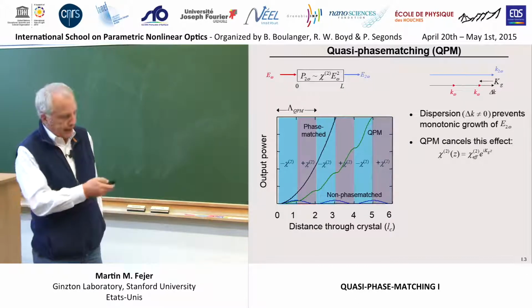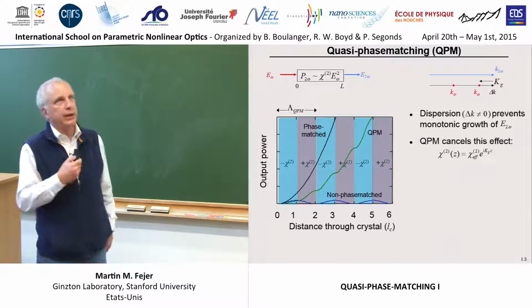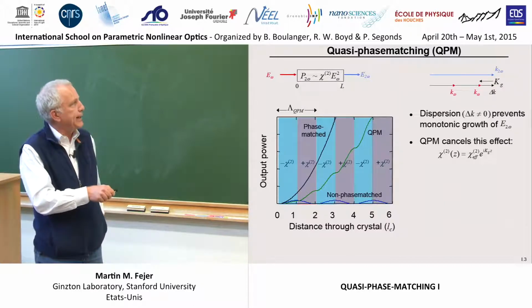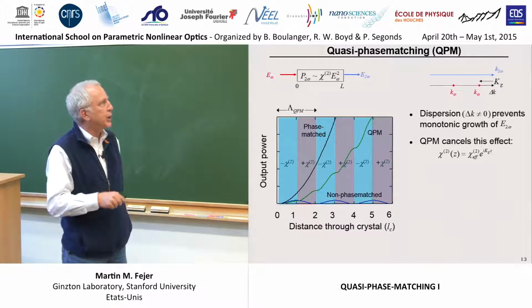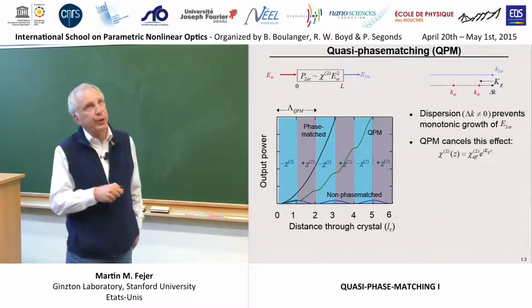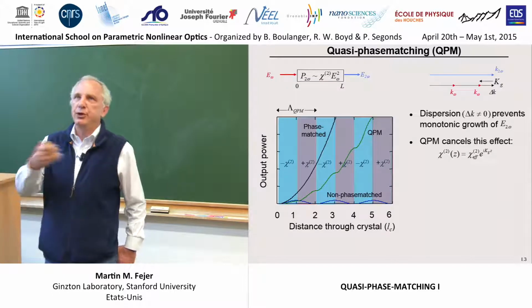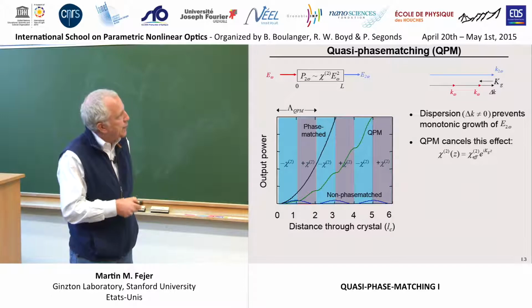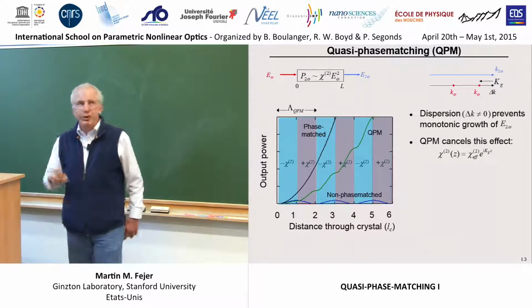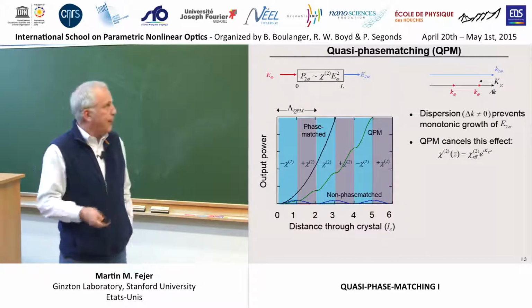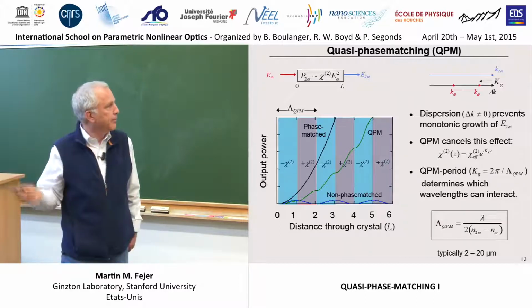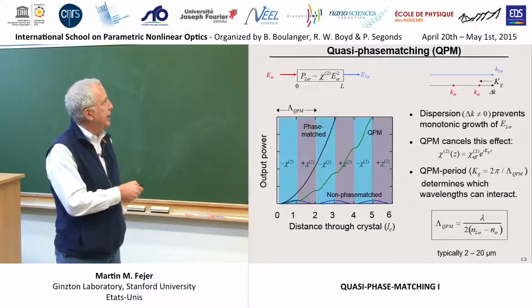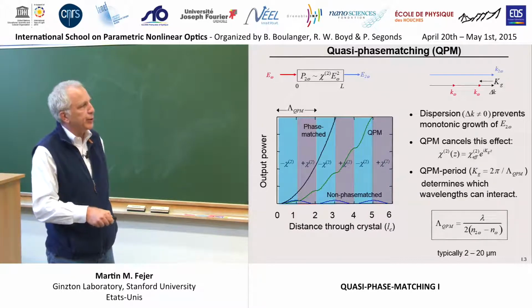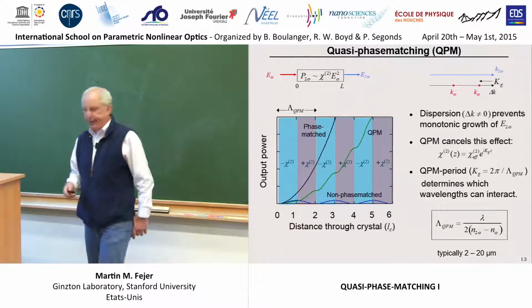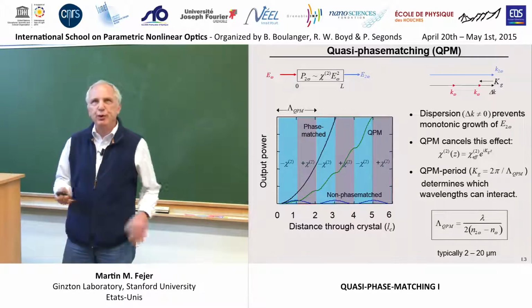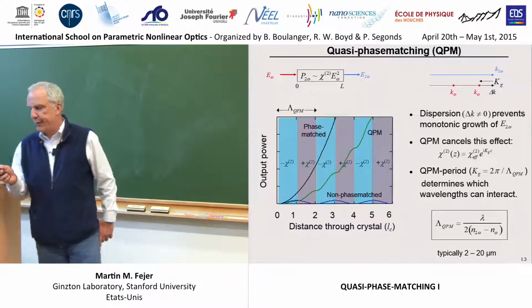An alternative, as we've also heard several times in the recent lectures, is quasi-phase matching. If one imposes a periodic sign change on the nonlinear susceptibility, adding an additional periodic structure and thus an additional k vector in the problem, one, instead of conserving momentum, can conserve something like a quasi-momentum to the extent that this periodic structure is just the right k vector to compensate for the phase velocity mismatch delta k. In such a situation, the required period for this structure is proportional to the wavelength and inversely proportional to the dispersion, the difference between the refractive index at the harmonic and the fundamental. And in typical cases, that's a few to a few tens of microns.